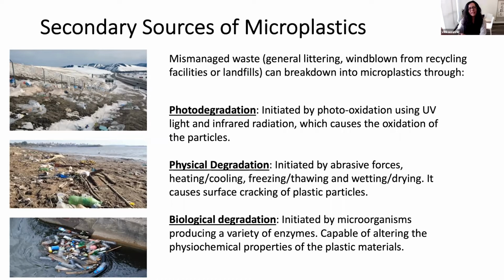Photodegradation is the most effective method to break down the chemical bonds that you can find in the polymers. But there is also going to be physical degradation of the plastic. As plastic moves across different surfaces, through abrasion and collisions, it is going to form smaller particles.